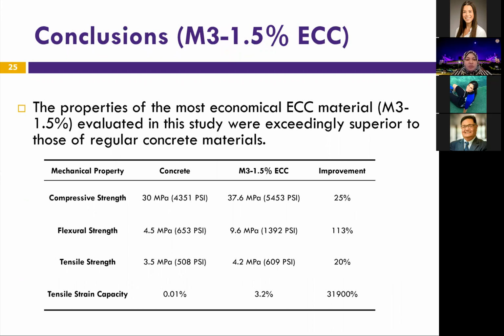This slide compares one of the mixes that we developed, M3 at 1.5% volume fraction of fibers, with regular concrete. And as you can see, it has 25% more compressive strength, 113% more flexural strength, 20% more tensile strength, and 31,900% increase in tensile strain capacity, which is amazing.